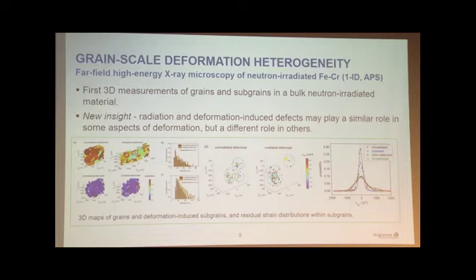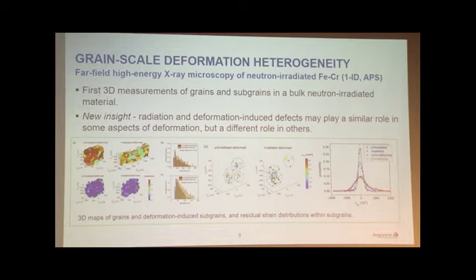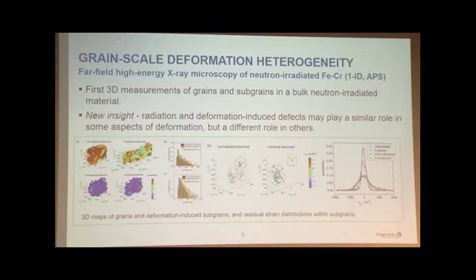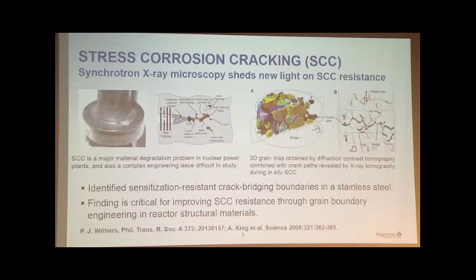And also, we measure the strain in each individual subgrain. It's quite interesting. So this is the residual strain distribution in the non-irradiated sample. If we irradiate, the residual strain distribution becomes much broader. And then if we deform, the residual strain distribution becomes even broader in the non-irradiated sample. But if we have radiation and deformation, interestingly, it looks just like a non-irradiated sample. So this technique basically tells us that when we look at the subgrain formation, radiation defects probably play one role. But when we look at the residual strain distribution, radiation and deformation defects probably play a very similar role.